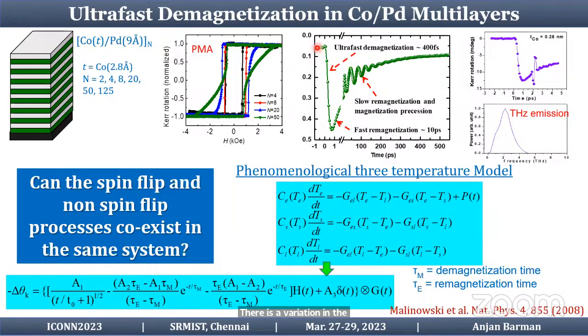So this is the time resolved dynamics. Here you can see the negative delay, the zero delay, the ultrafast demagnetization, relaxation, and the damped precessional dynamics in the system. These also show a terahertz emission at about 3 terahertz after the demagnetization, which shows that terahertz emission can have a role in the demagnetization as well.